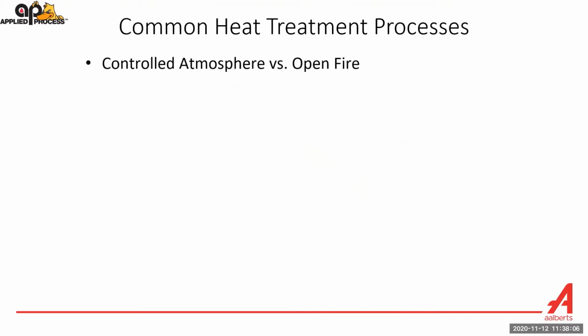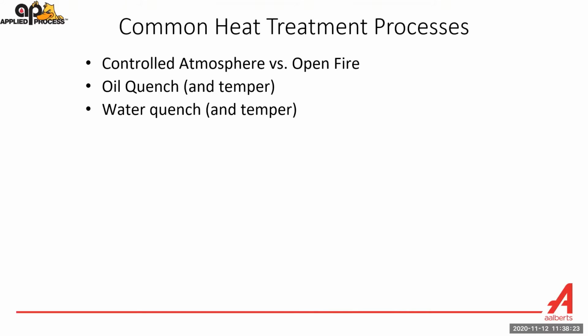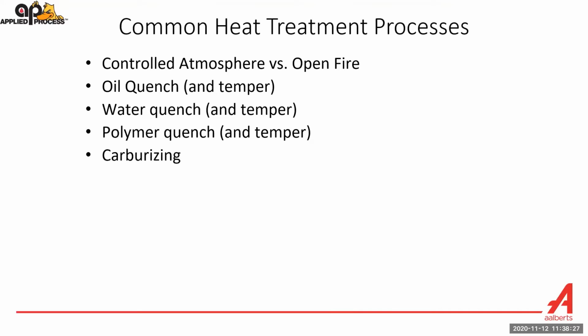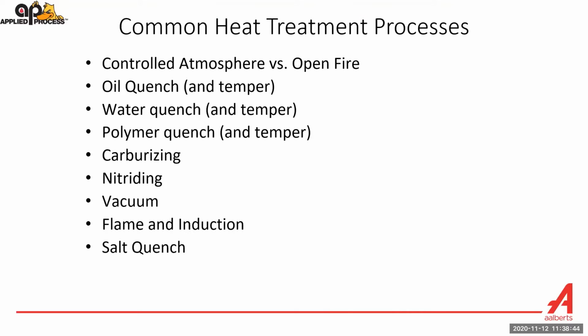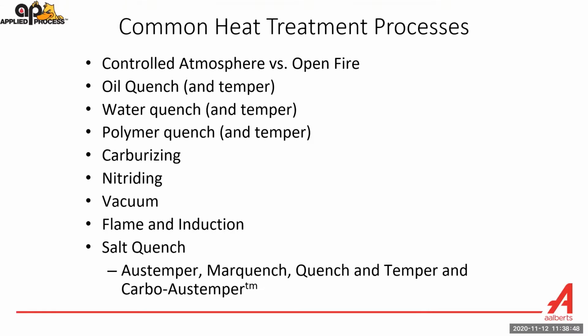Common heat treatment processes that are out there: you can heat parts up before you quench them in a controlled atmosphere, or you can do it in open fire in the presence of oxygen. There's oil quenching, which is probably the most common type of heat treatment that's done, and you have to come back and temper the parts. There's water quenching and tempering. There's polymer quenching and tempering. There's carburizing, where you enrich the surface of the part with carbon to improve the hardenability and hardness. There's nitriding, where you add nitrogen to the surface of the part to increase the hardness. You can do vacuum heat treatment, flame and induction. And then there's this unique thing called salt quenching. Through that process, you can do Austempering, Marquenching, Quench and Temper, Carbo-Austempering, different things.